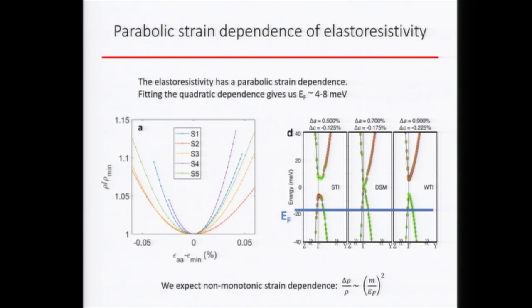How much is the distribution for this epsilon min? Do most of the crystals have a very similar minimum epsilon you have to apply, or can it be very different? It actually depends more on how you glue the crystal and how it cools down. In fact, we try to track the intrinsic epsilon min, but usually you lose track around 40 to 50 Kelvin. Somehow, you just have some thermal expansion strain that you cannot compensate during that.